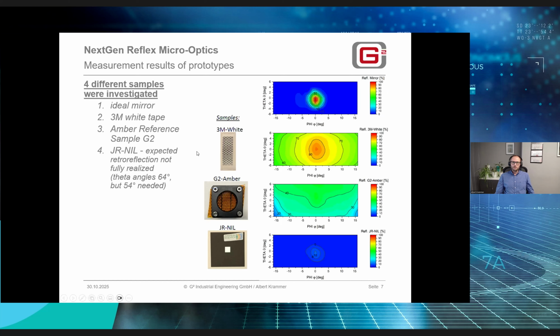The second one was a typical white tape, which is available on the market, used for different applications like trailers or agricultural machines, wherever there are no strict laws, but you need some reflectance to see the machines. Here, the quality was surprisingly good. You can see it in the second top picture from above. The reflectance was about 80 to close to 90% over a quite acceptable angle for this application. You have to imagine these tapes you can buy meter by meter, so it's no small device, and this quality over a high volume production is quite good.